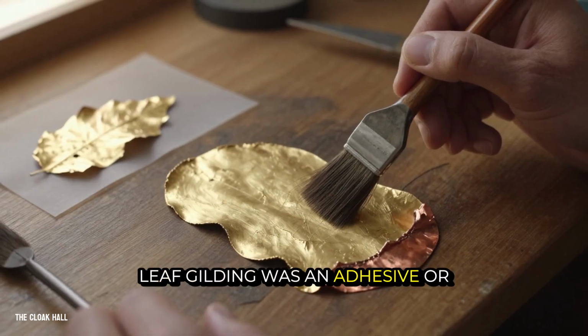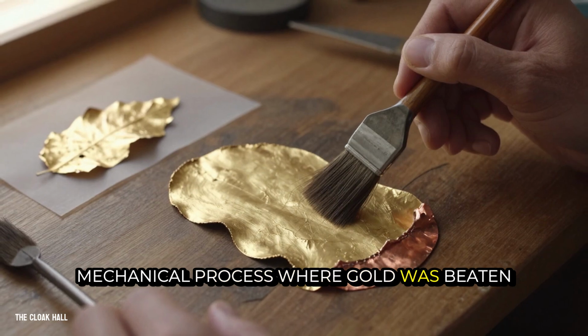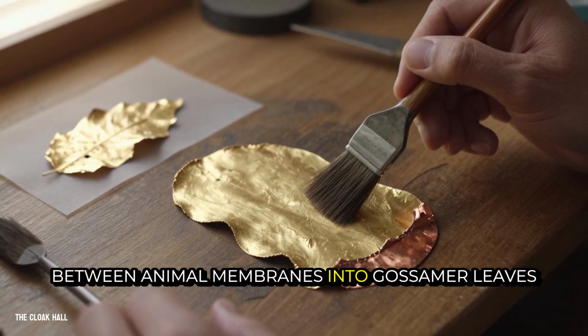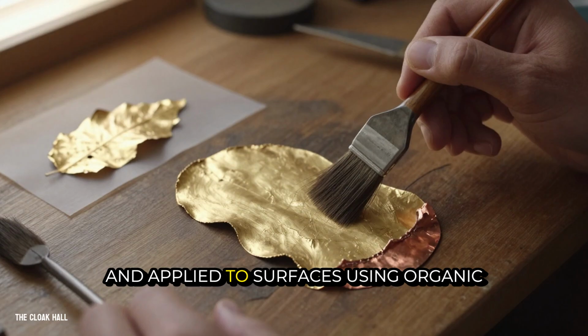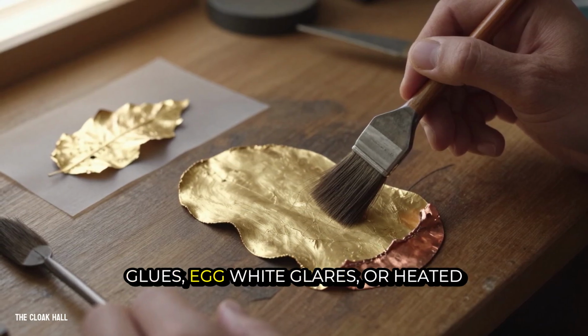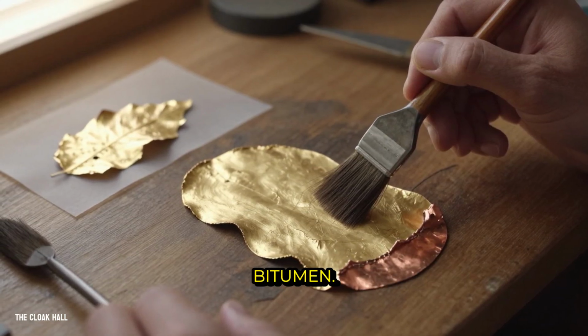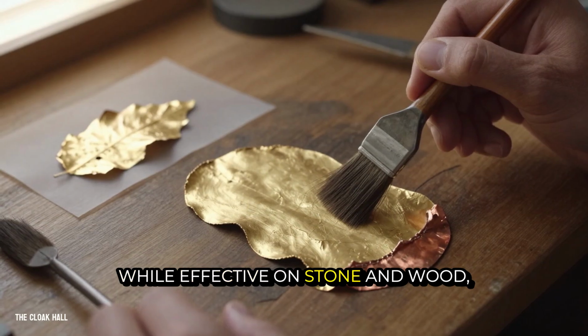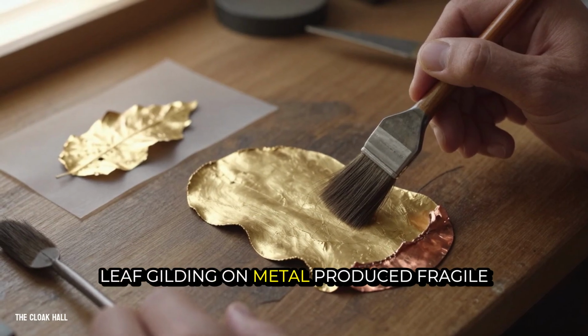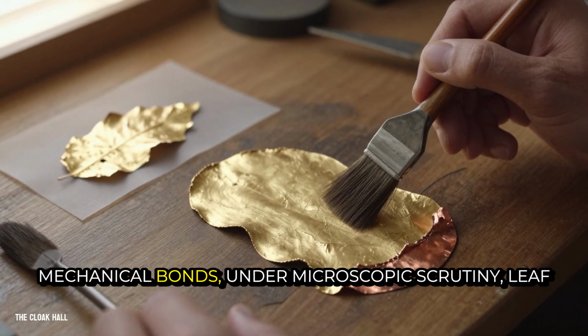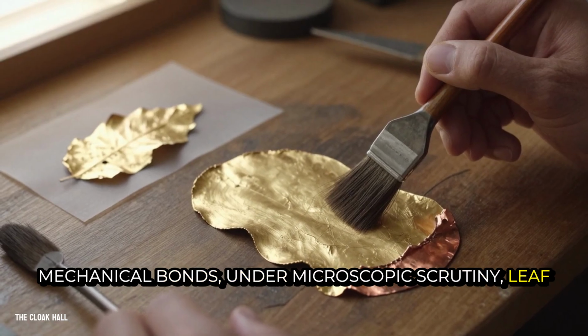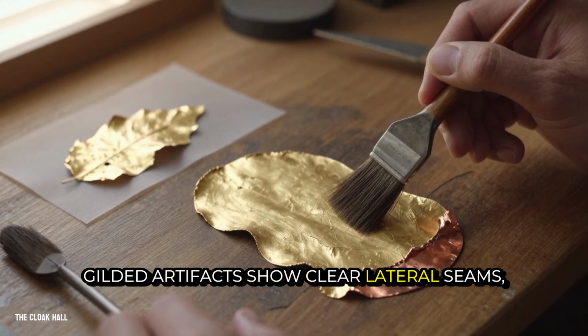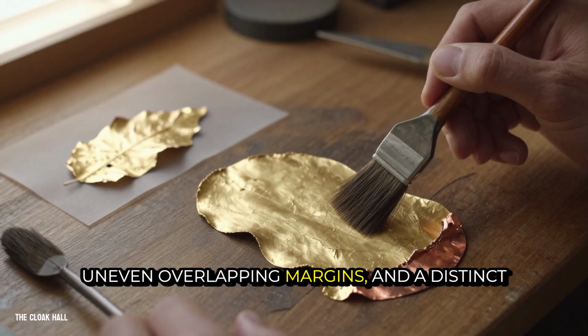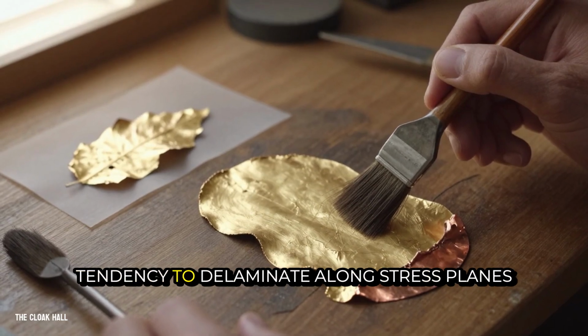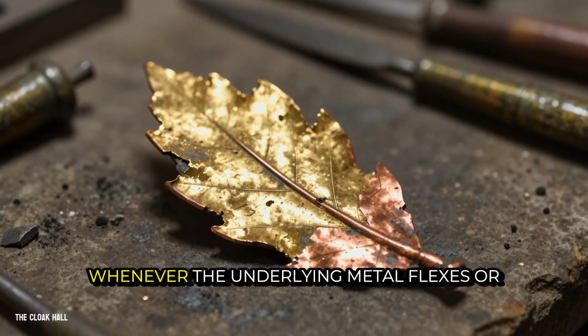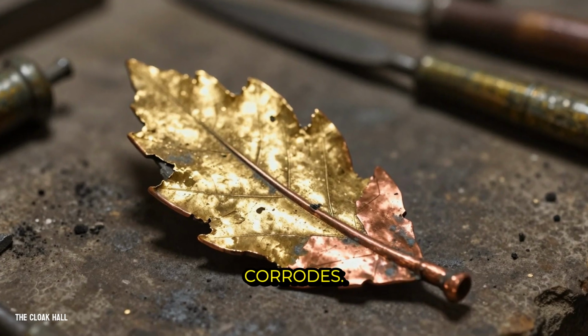Leaf gilding was an adhesive or mechanical process where gold was beaten between animal membranes into gossamer leaves and applied to surfaces using organic glues, egg white glaires, or heated bitumen. While effective on stone and wood, leaf gilding on metal produced fragile mechanical bonds. Under microscopic scrutiny, leaf-gilded artifacts show clear lateral seams, uneven overlapping margins, and a distinct tendency to delaminate along stress planes whenever the underlying metal flexes or corrodes.